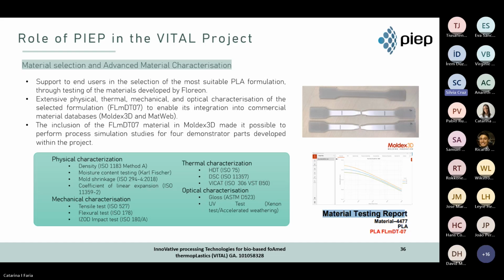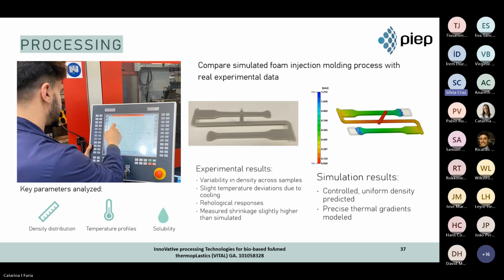The inclusion of this material in Moldex 3D made it possible to perform process simulation studies for the 4 demo cases that were studied and developed within the project. After preliminary test trials for determination of the foaming agent solubility in the material, to update foaming agent info versus material in the software, we conducted simulations of the process and compared with the real experimental data.